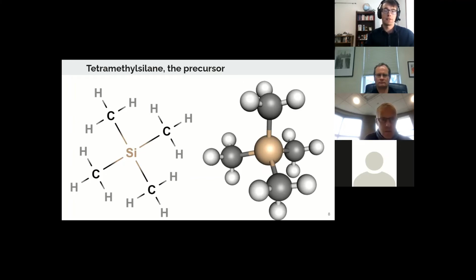TMS has been used to make silicon carbide nanoparticles and thin films in prior research. It's a fairly well-used precursor, which is another reason we're using it here. As TMS has a carbon to silicon ratio of 4:1 in molecular form, that is, for every 4 carbons, there's 1 silicon atom, prior literature reports indicate an excess of carbon in the final formed nanomaterial.